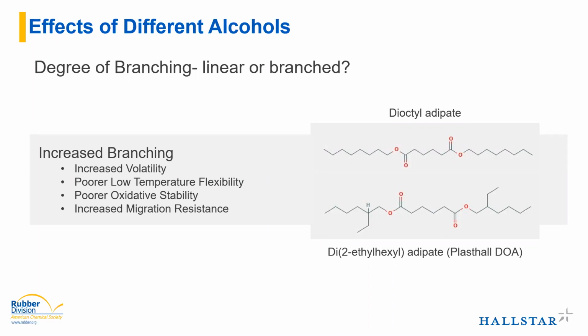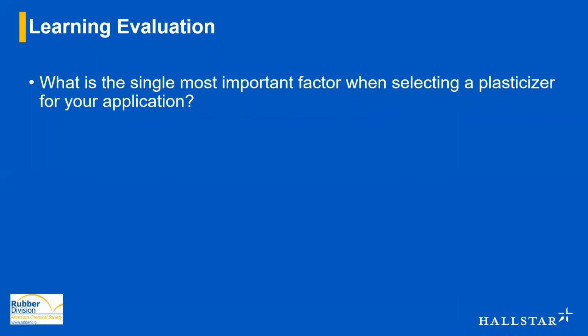But what it does for you is it helps to increase your migration resistance. Like I said, with the material being entangled in the polymer matrix, you won't see as much migration because your plasticizer won't be able to move as freely. So it's more likely to stay in your compound over time.